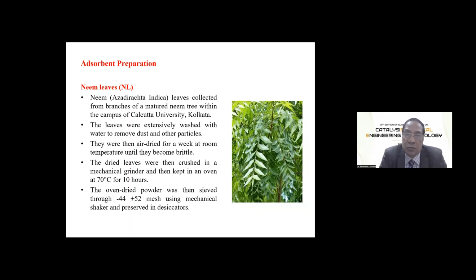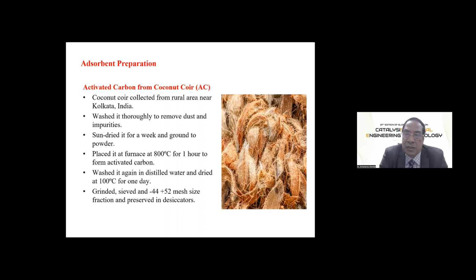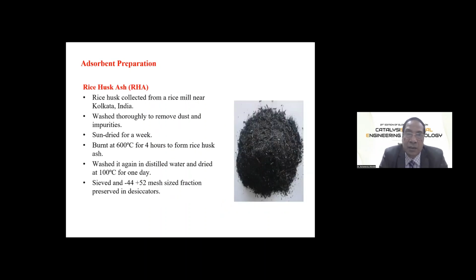This is the coconut coir, but instead of utilizing the direct coconut coir, we have made the activated carbon by taking it, after washing, in a furnace and maintaining it at 800 degrees centigrade for 1 hour. Then the powder has been utilized as adsorbent. This is rice husk ash we have collected from the rice mill, where the rice husk is utilized for small scale industries as a fuel.